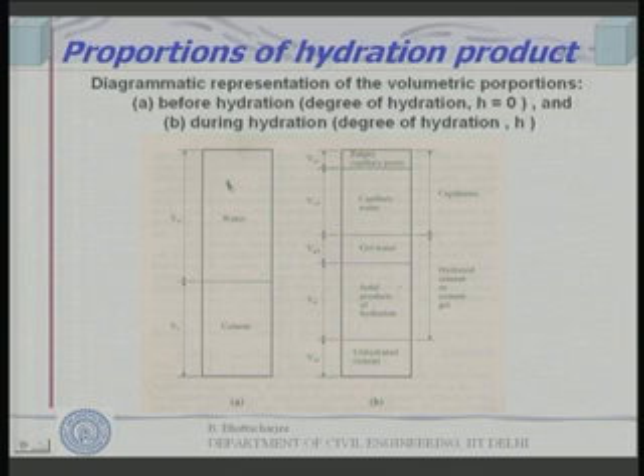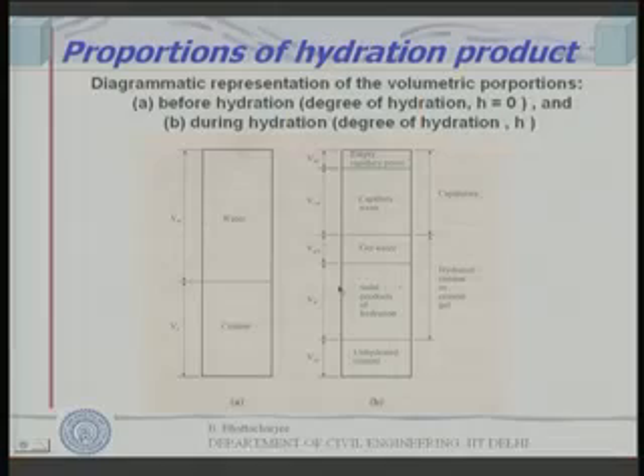if I look into a diagram, see initially I had cement and water, a schematic diagram, and this has got a volume, let us say VW, and this is the VC, volume of cement. Then after hydration what will happen? I will have some unhydrated cement that we have seen from the BSE images. You will have some solid product of hydration, and this is associated with some amount of porosity, right, gel porosity. This is inherent. These pores are occupied by water, we call as gel water.